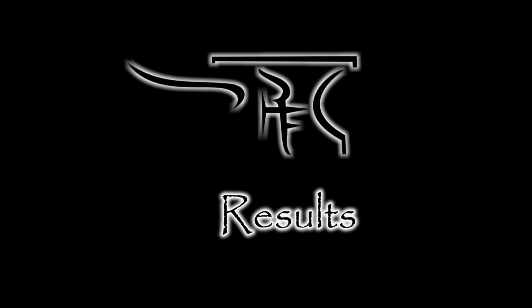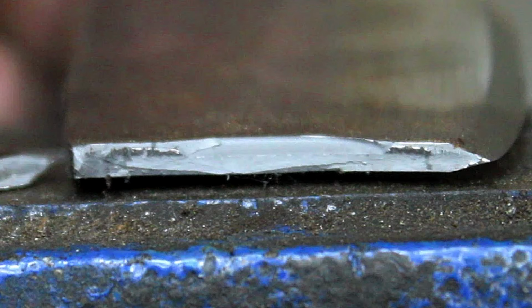All right, now that was an adventure right there. Let me tell you what. So let's take a look at this break. The first thing that jumps out at me is the grain structure. It's extremely fine, very tight, and has that silky, almost matte appearance that you want to see when you're looking at a fractured surface. We don't see any of that coarse, crystal-like structure that would immediately make me think we overheated the steel. Looking at this break, I'm pretty happy with the heat treatment.